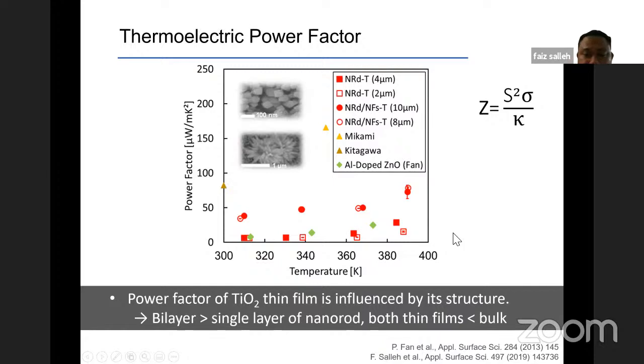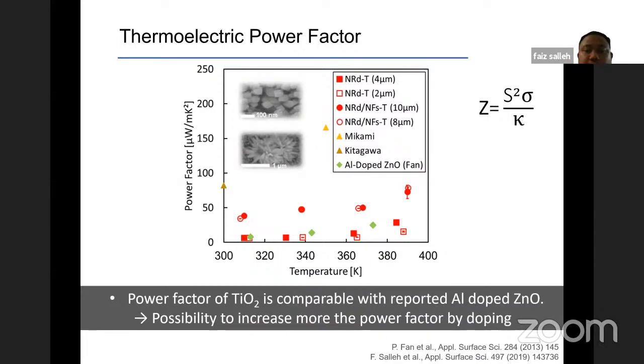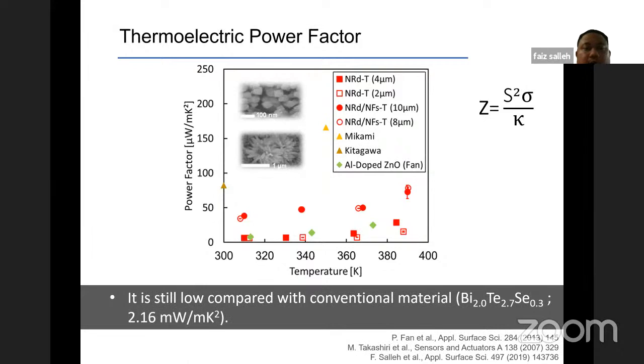Okay, so if we compare with the reported aluminium-doped zinc oxide, we can see that our bilayer is much larger than the thermoelectric power factor of the aluminium-doped zinc oxide. We are still not using doping inside that nanostructured TiO2, so we can expect a possible further increase in the thermoelectric power factor by using doping. However, if we compare with conventional material like the telluride-based material, it's still very far, still low. So there are still more challenges to improve this thermoelectric power factor.